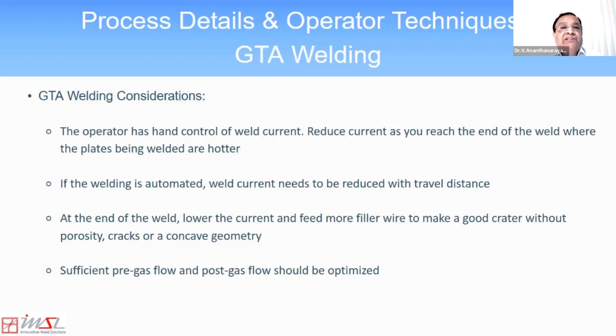When you do gas tungsten arc welding, the operator has hand control of the welding current, and you need to reduce the current as you reach the end of the plates being welded as they are hotter. And if the welding is automated, the welding current needs to be reduced with travel distance. And at the end of the weld, lower the current and feed more filler wire to make a good crater as well. And sufficient pre-gas flow and post-gas flow should both be optimized.